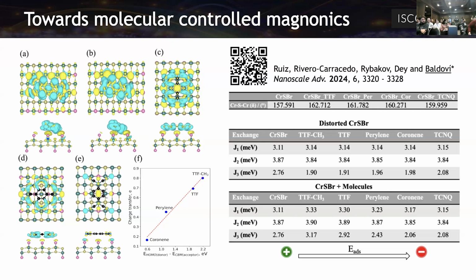Yeah, exactly, because with light you can generate already the spin wave, and you could control it, but the advantage here of the molecule is that you can fine-tune the frequencies. You can fine-tune this effect, for example, we replace a hydrogen by a methyl group, and then we change the doping, and this is having an effect. So it's a way of controlling using a chemical design, no? Which is the best molecule to induce. But of course, with light, it's possible to generate the spin waves and also to modulate the spin waves.